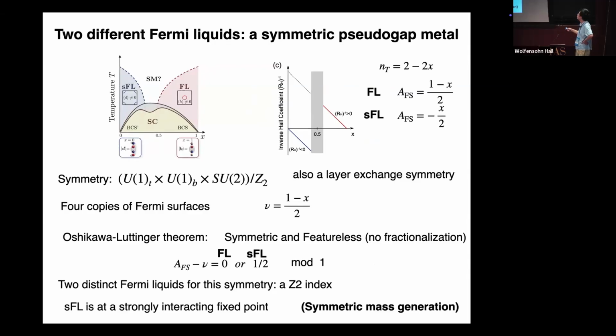So these two regimes are really BCS. But we have this, which is like an analog of pseudogap metal in cuprates. Because at X equal to 0 you actually have 2 electrons per site, so in the free Fermi model you would expect a large Fermi surface, but actually you have a gap, so it's like a pseudogap metal. For the transition, I don't know. There must be a transition. I don't want to talk about it. Maybe I just want to mention this second Fermi liquid is very similar to the FL* Subir talked about. It's basically FL* made by making the spin liquid a round singlet. So this is the analog.